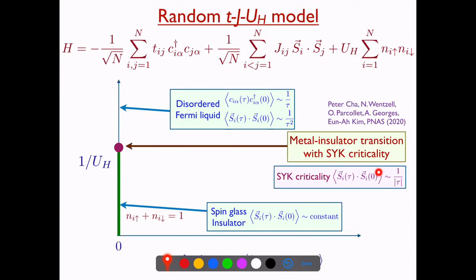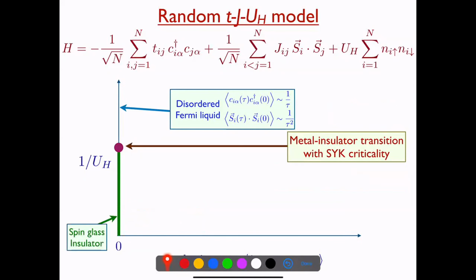But what you see then are the 2 things happening at this critical point. One is the opening of a charge gap, and the other is the onset of spin glass order. These need not have happened at the same point. You could have had a metallic spin glass. There's nothing wrong with having a metal which is also a spin glass. In fact, very soon I'm going to talk about such a state. But that doesn't seem to appear. So that suggests that this is a non-Landau type phase transition, or deconfined critical point. Okay. And we'll find more evidence for that as we go along.